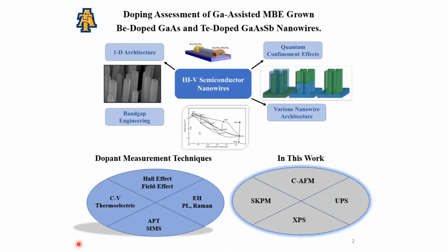In this work, we evaluate the carrier concentration and incorporation of beryllium dopants in gallium arsenide nanowires and tellurium dopants in gallium arsenide antimonide nanowires grown using gallium-assisted molecular beam epitaxy with variation in beryllium cell temperatures from 750 degrees Celsius to 950 degrees Celsius and gallium telluride cell temperatures from 500 degrees Celsius to 570 degrees Celsius respectively, using conductive atomic force microscopy, scanning Kelvin probe microscopy, X-ray photoelectron spectroscopy, and ultraviolet photoelectron spectroscopy, as they do not involve any contact fabrications.